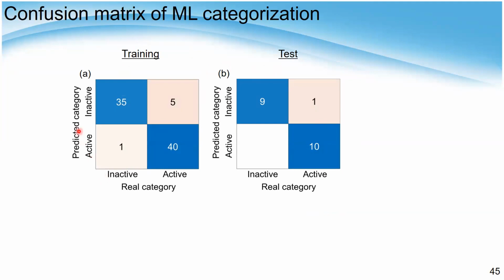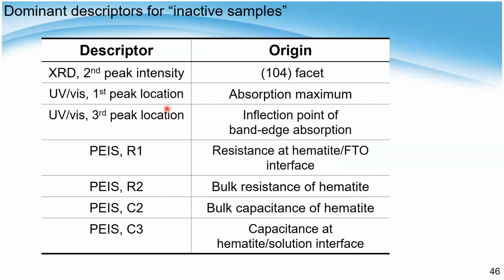In categorization machine learning, we can obtain the confusion matrix instead of the response plot. What it means is this is the real category and this is the prediction category. A real inactive sample predicted as inactive comes to this part, and the active one predicted as active is here. So the diagonal numbers indicate the correct predictions, and the others are incorrect predictions. For the training and the test data sets, we could mostly predict the active and inactive categories nicely. And during this process, we can determine the dominant descriptors.